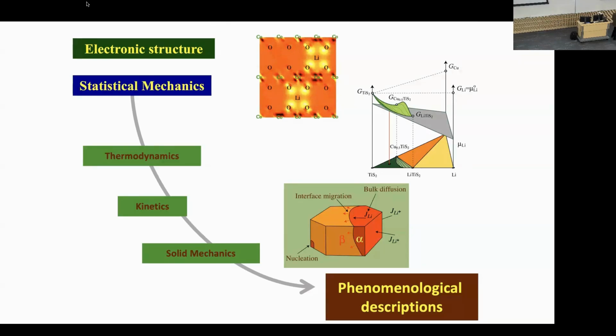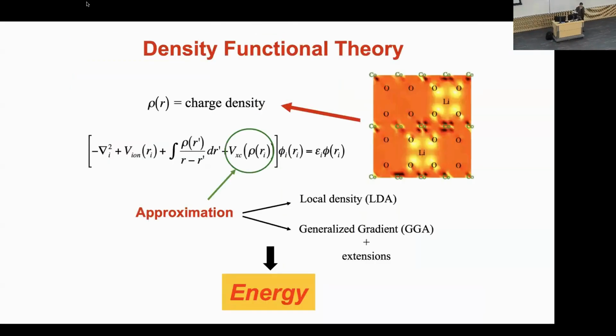And a lot of that will rely on statistical mechanics, because these are all thermally activated processes. So temperature is very important. Entropy is very important. And so with statistical mechanics, we can predict thermodynamic properties, kinetic properties like diffusion coefficients, and increasingly solid mechanics properties. The starting point, without going into too many details, is a first principles method to tackle the electronic structure problem. The workhorse nowadays is density functional theory. There are some add-ons to improve it for more complicated systems like transition metal oxides, but I won't go into details.